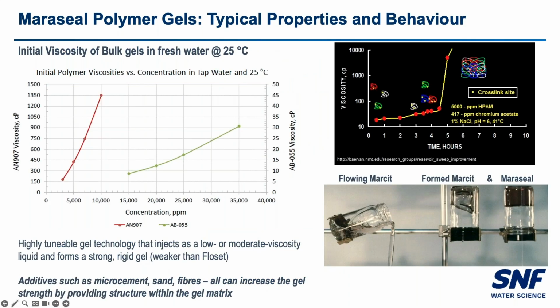Just in terms of the typical properties and behavior for these MeriSeal polymer gels, another product we have is a Marcit gel, which is a higher molecular weight polymer. So we use our AN907 polymer versus the AB55. The AB55 forms a more robust gel. So you see in the picture in the bottom right corner, the MeriSeal forms a ringing gel, so it's very little surface deformation. And the initial viscosities on these, if we look at the green curve on the bulk viscosities, at concentrations down at 15,000, we're under 10 centipoise. So we're getting very water-like initial viscosities. So these can easily flow into fractures, fissures, flow behind pipe, etc.